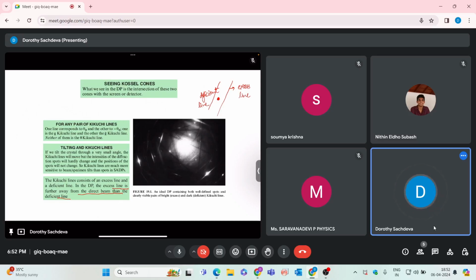So in this diagram, you can clearly see that you are able to see these diffracted spots along with this central spot, and also you are able to see these Kikuchi bands as well, right? So all these bands are visible. One line will correspond to theta B and the other line will correspond to minus theta B. So one is the G Kikuchi line and the other will be the bar G Kikuchi line. Neither of them will be the zero Kikuchi line.